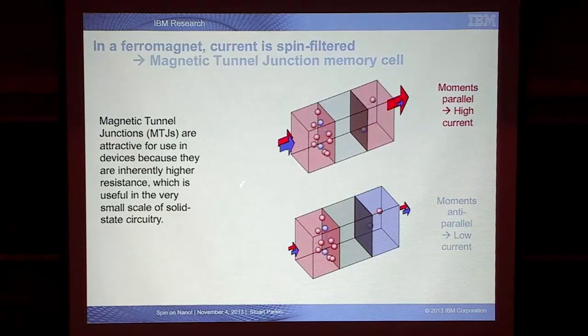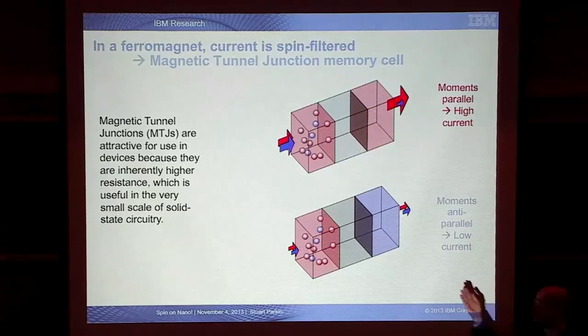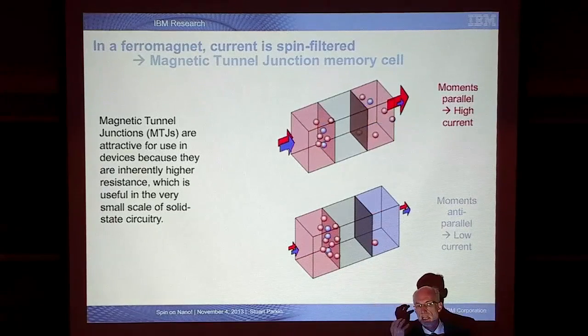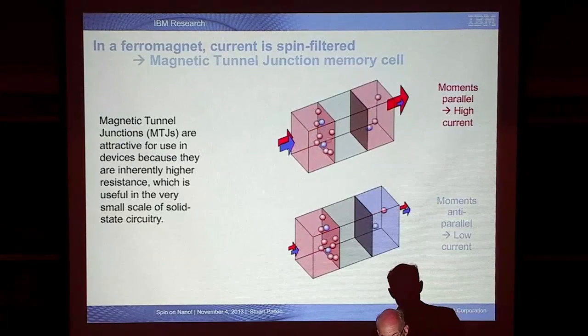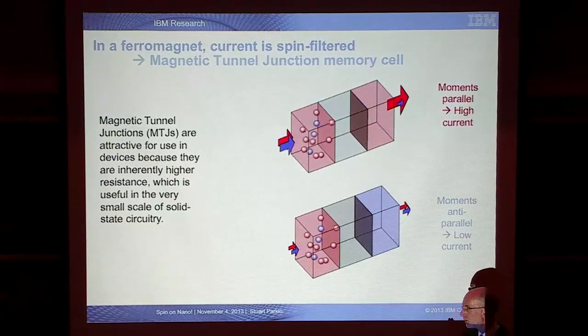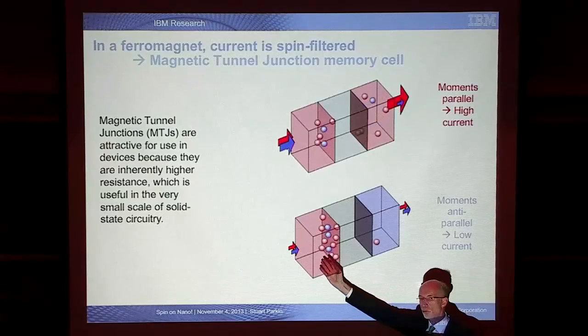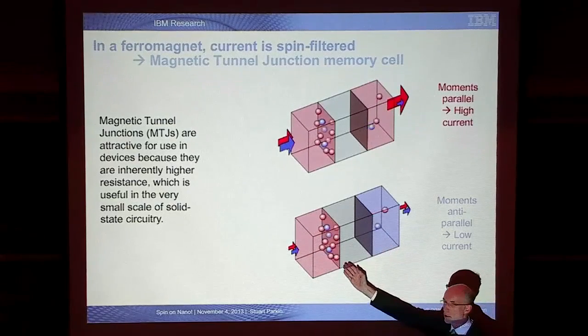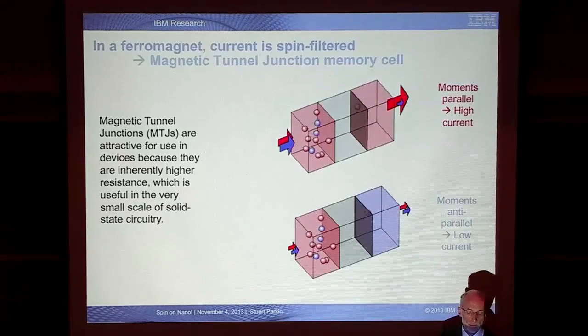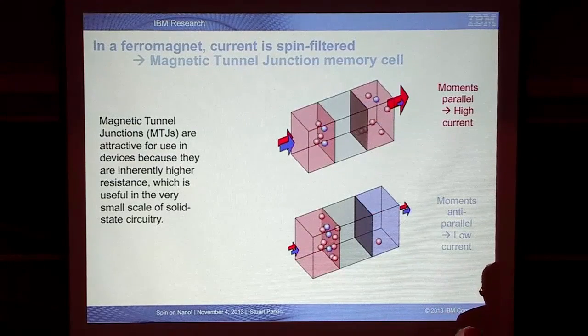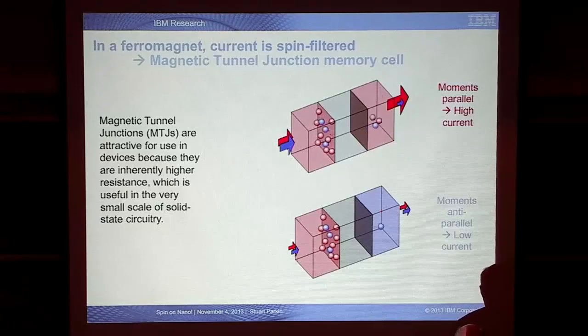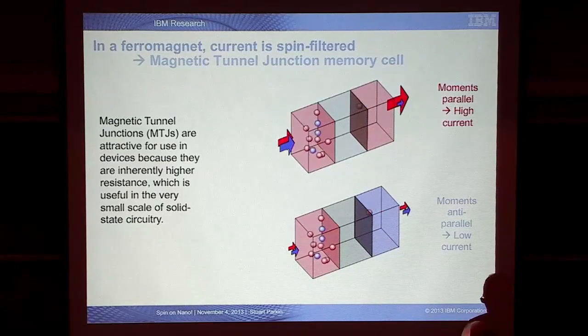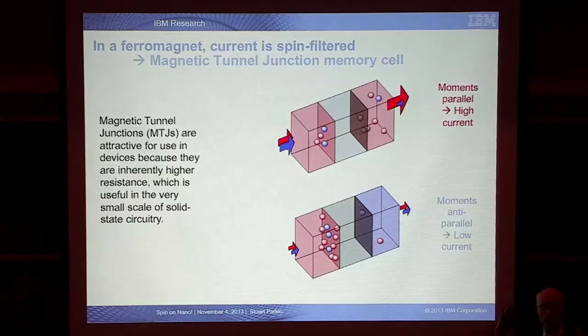Again, it's similar. We have a sandwich of 2 magnetic layers. Here again, they're shown color-coded red and blue, depending upon their magnetic orientation. But now, instead of having a metallic layer separating these magnetic films, we have an insulating layer, a dielectric material, or even air. Now, the physics is totally different, and the current is going to flow from one magnetic layer to the other across this insulating dielectric material. And now the probability of electrons quantum mechanically tunneling across essentially an insulator depends on the orientation of these magnetic films.